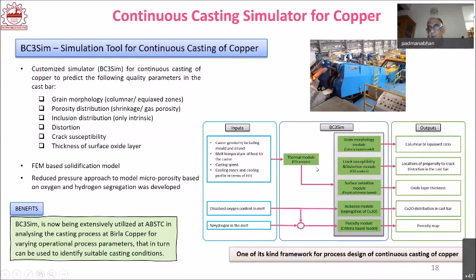And then, in an industrial plant, you cannot have a totally inert atmosphere. So the air is there, and therefore surface oxidation cannot be avoided. By understanding the real situation that exists there, you will be able to predict the likely oxide layer thickness. In addition, the material we are talking about here is what is called in industry pitch copper. Pitch copper is copper with about 200 ppm of oxygen. And therefore, as far as inclusion formation is concerned, we are considering only inclusions of copper oxide. So you consider the copper-oxygen binary diagram and find out the eutectic point, and there you will be able to work out the Cu2O distribution in the cast material.